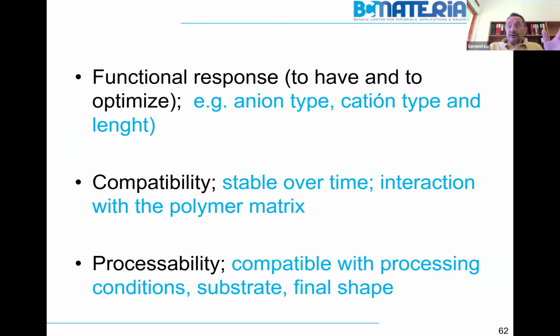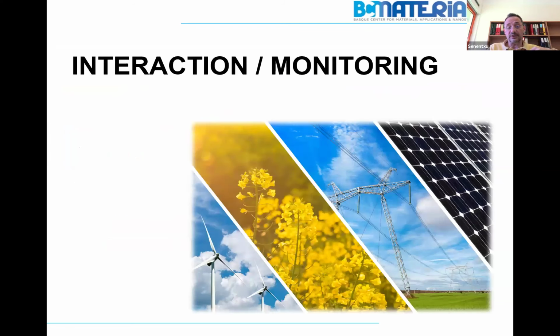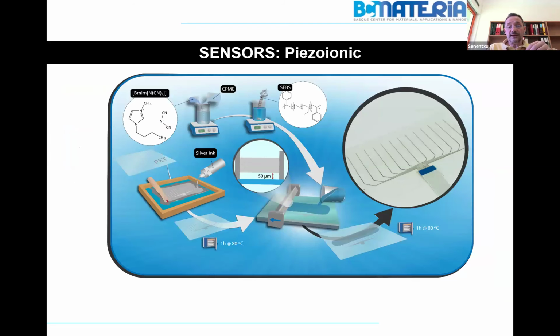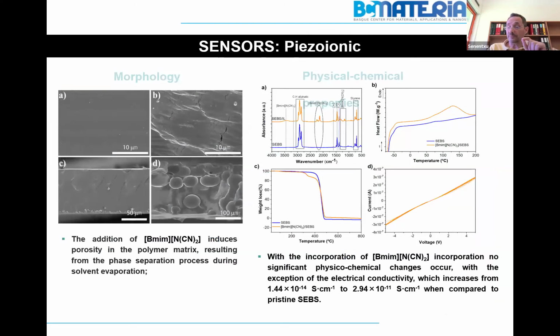By anion type or cation type, you get the functional response. By tuning anion and cation, also the stability with the matrix and also the rheology, that means the compatibility with the processability. One example, piezoionic response. You see, we use a highly conductive ionic liquid into a polymer matrix.